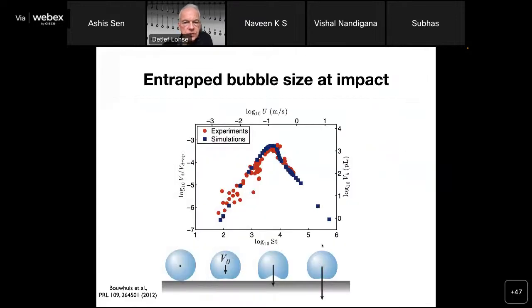And so out of this, we extract the dimple size. In fact, this is the volume of the dimple, of the bubble, divided by the volume of the drop, versus the Stokes number. The Stokes number is basically the non-dimensionalized velocity. So here I also plot velocity, and here I plot the absolute volume of this entrained bubble in picoliters. So you see it's tiny. And what's most remarkable is, on first sight of this plot, that without any parameters we can calculate this, and how we calculate this I show you in a second.